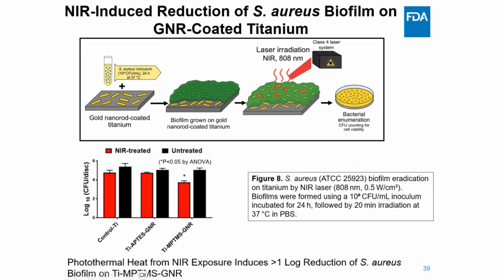After confirming the photothermal heating potential of the gold nanorod-coated surfaces, we next ask whether this heat could be used to reduce bacterial biofilms. As you can see here, Staphylococcus aureus biofilms were grown for 24 hours on gold nanorod-coated titanium, then exposed to NIR light as previously shown. Titanium surfaces treated with gold nanorods via MPTMS showed over a 1 log reduction in viable bacteria after 20 minutes of irradiation, which is significantly greater than what we saw for biofilm reduction in APTES treated titanium surfaces. So this demonstrates the enhanced photothermal anti-biofilm effects of MPTMS-based coating.